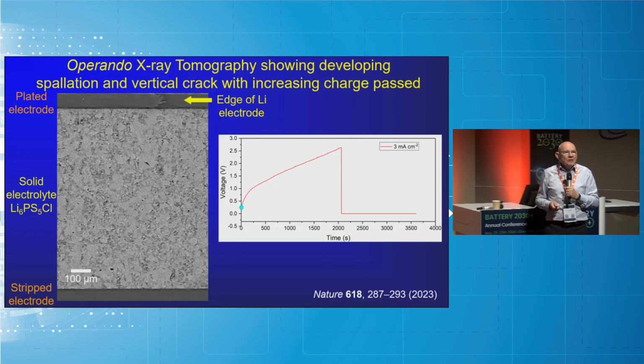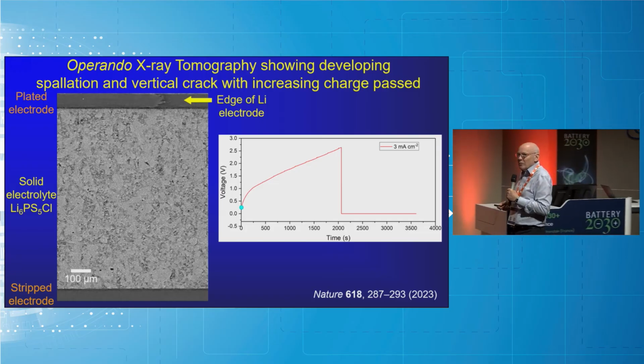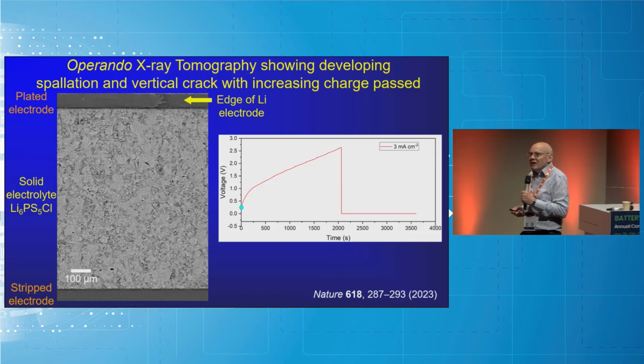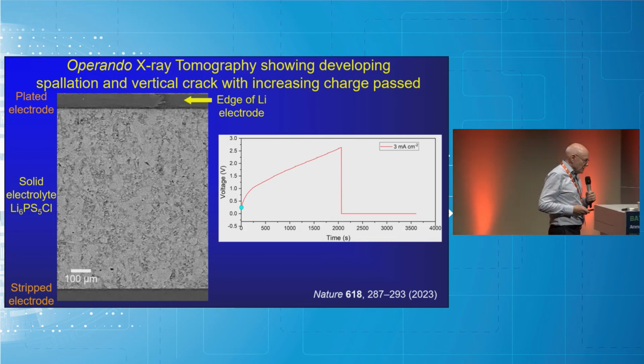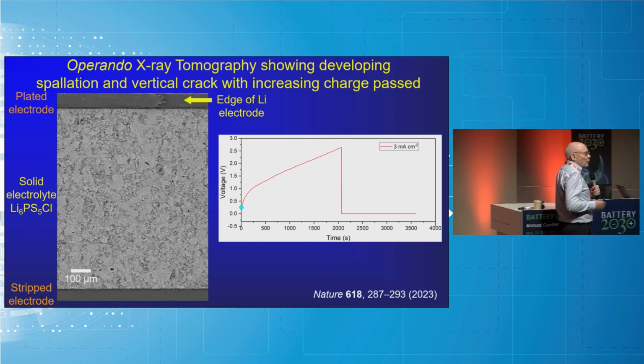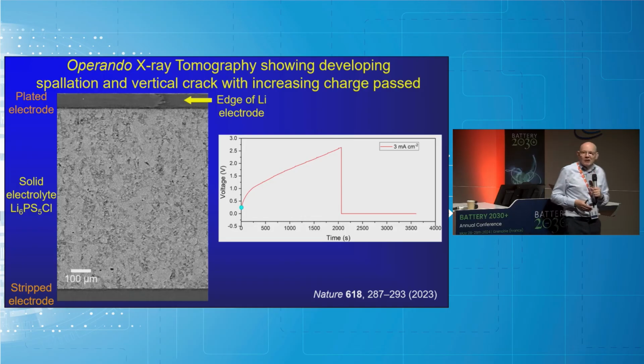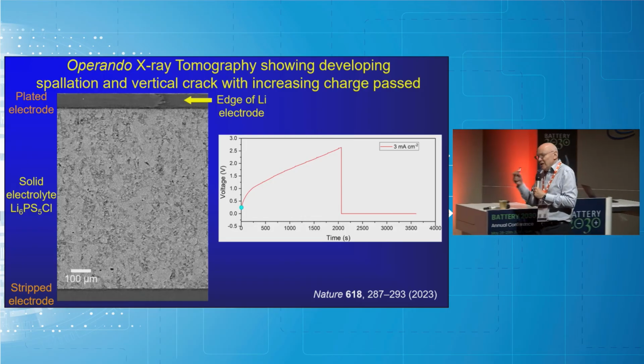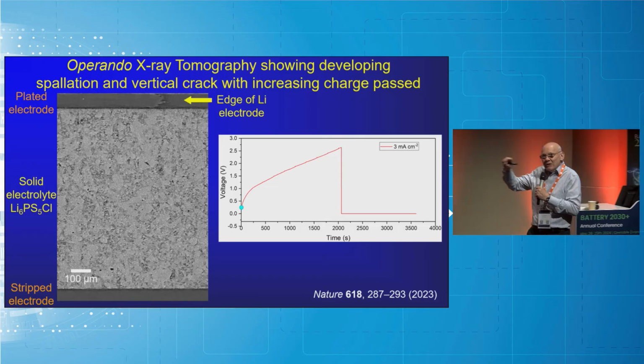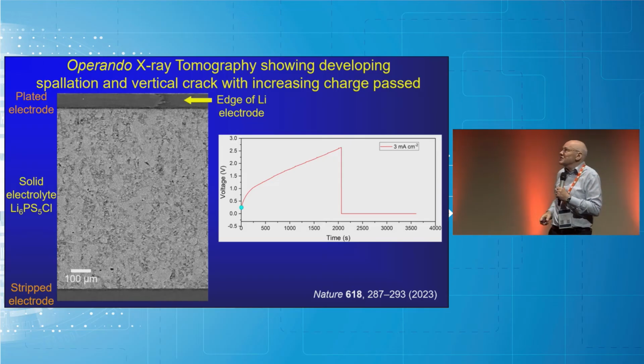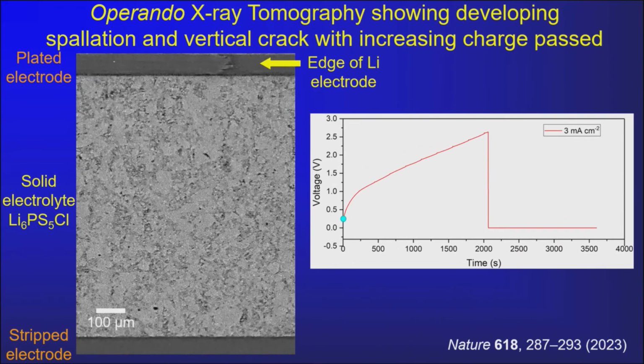The big problem with lithium metal anodes, whether it's in liquids or polymer electrolytes or ceramics, is of course the problem of lithium dendrites. It shouldn't really be called dendrites in ceramics, but I'll still use that term. In the ceramics, it's fingers of lithium, filaments of lithium that penetrate even relatively dense polycrystalline ceramics when you charge the battery. So when you charge above a certain rate, certain current density, these dendrites form, pass across the ceramic electrolyte and short the battery, which is obviously catastrophic and needs to be avoided.